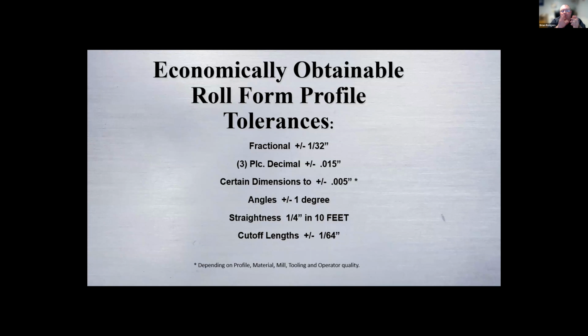And then cutoff lengths, plus or minus a 64th. I've seen tighter than that also, plus or minus 30 thousandths of an inch. It depends on what your product is. I do a lot of estimating and different things and putting lines together. And my thing is, I need to know what is important to you, because if I sell you a machine that holds plus or minus 30 thousandths of an inch, and you're just measuring it with a tape measure and you don't care if it's within a 1/2 inch, I could end up selling you the wrong type of machine that will hold that tight tolerance when you don't need that. And we can focus on what you're really needing.